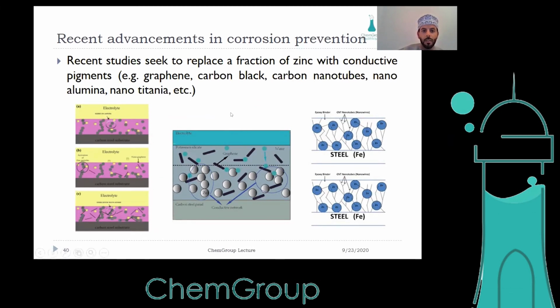The mechanism of this protection is not proven, because as we know, if we go back to the electrode potential, the carbon is very cathodic in comparison, more stable in comparison with steel and zinc itself. So imagine if there is a corrosion cell between graphene or carbon and steel, the steel will corrode faster than before. So this research is of recent interest, but the exact mechanism is not well understood.